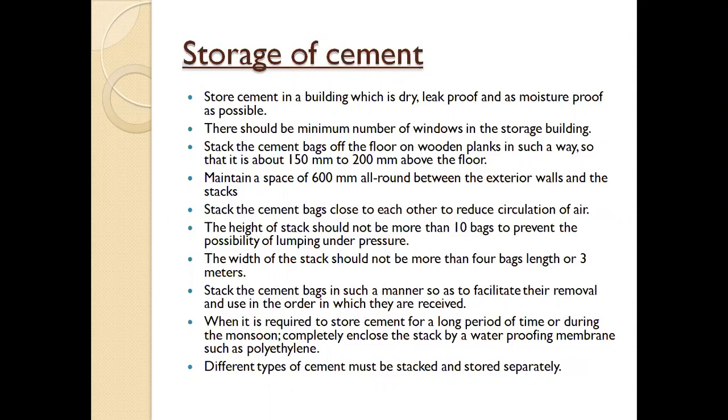There should be some arrangement made such that the cement bags are stored about 150 mm to 200 mm above the floor or ground. Maintain a space of 600 mm all around between the exterior wall and the stacks. So while storing the cement, there should be a gap of minimum 600 mm all around the walls, and the stacks should also have a 600 mm gap between them.